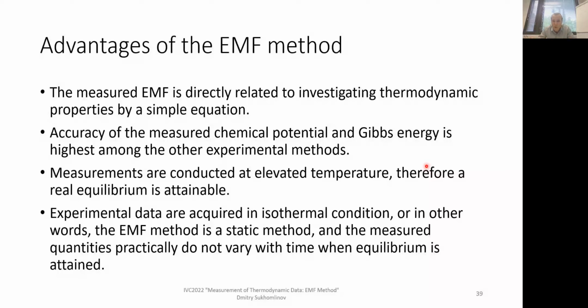But for silver concentration cells, equilibration might be really slow. When we work with silver iodide, temperature can be around 300. So it's somewhat quick, but not that quick. But then there are electrolytes which behave as pure ion conductors, silver ion conductors, at even lower temperatures, even from room temperature onwards. Silver rubidium iodide, for instance. And then at room temperature, at 50 degrees, equilibration might take days and weeks. But in general, it's a relatively quick method.